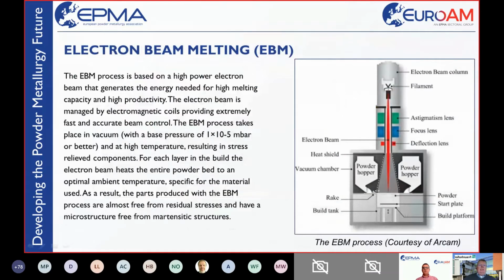Electron beam melting is a bit different. It takes place under vacuum—that's the first big difference—and it has an electron beam instead of a laser beam as an energy source. The laser process takes place under protective gas, mostly nitrogen or argon, depending on the material used. As said, EBM does the same in vacuum, which is necessary for the electron beam to be scannable in the end.